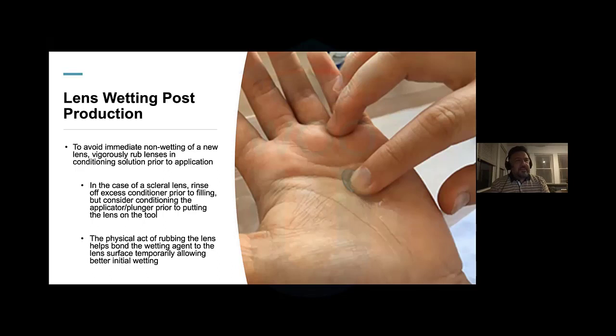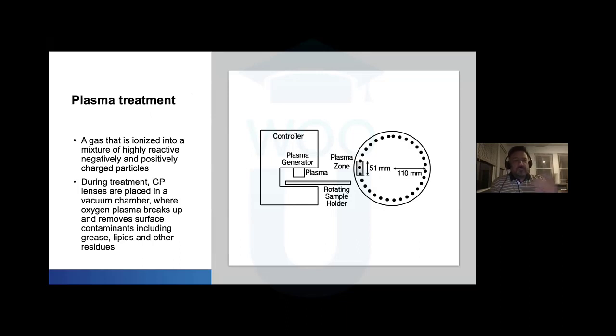But I think sometimes, again, we neglect to think about the value of that conditioning step in the wettability of a lens material when we go to put that lens on. So again, wanted to mention the plasma treatment. Plasma treatment is something that's done in the lab. The lens is manufactured, it's released from the mold, whatever holds it as it's lathed, and then it's placed into a chamber with a mixture of ionized particles. Will bombard the surface and remove residual residue and contaminants that might come about through the manufacturing process.